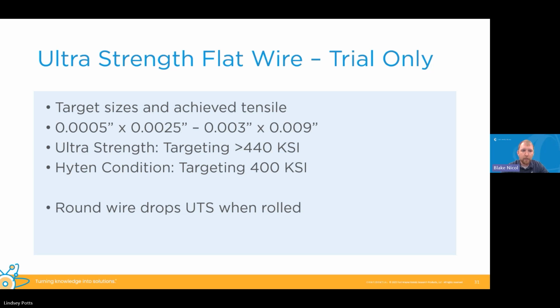Just to give some equivalencies on tensile as well. Our highest condition we used to have is Hyten, where we were targeting around 400 KSI depending on size. As you get the size bigger, the tensile will decrease a little bit. Then we also have our ultra strength, which we're now exploring with flat wire as well, where we've been seeing some tensile strengths of 450, 440, and almost getting up to 460 KSI.